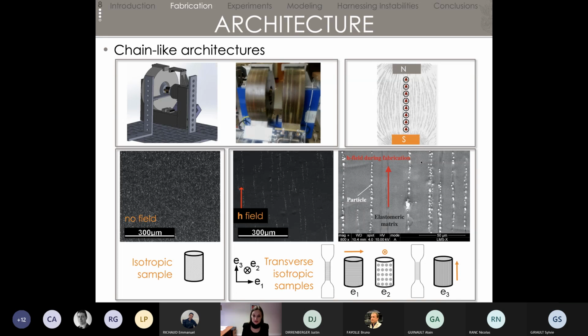And those chains or those columns will be locked in place as the material is cured. So that gives us transverse isotropic samples, and in our case, we created those chains or columns in the 3 principal directions of the sample. So you can see those alignments of chains here on those SEM images. Another and last point about the samples is the shape.